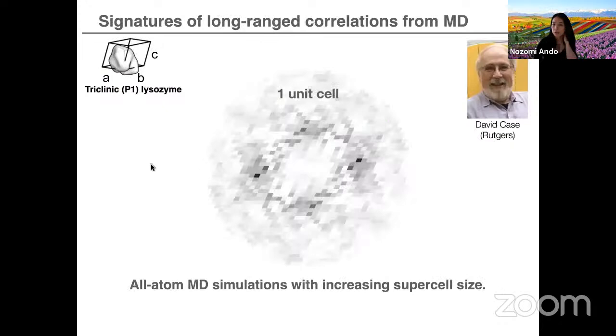Okay, in our collaboration with David Case, we also took a different approach to try to understand these halos. And he had done multiple really giant, long, full atom MD simulations of the same crystal system. So here I'm showing diffuse scattering simulated from a one unit cell simulation. What I mean there is that he took one unit cell and then put periodic boundaries, turning it into a crystal and then doing a simulation. And if you do that simulation, allow it to converge and calculate the diffuse scattering, you see a continuous pattern that's not very sharp anywhere.